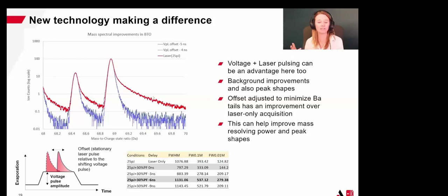Now, as we saw earlier in this webinar, the mass spectrum of these materials is really complicated. So you can have minor elements that are occurring in the tails of another peak, making it really hard to determine how to range that data. So one thing I'd like to show you here is we can compare laser pulsing here in red.